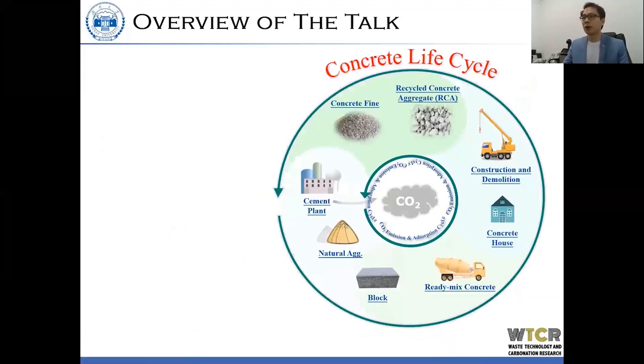Now a brief overview of what I'm going to look into today. The role of CO2, or how CO2 can make the concrete life cycle more sustainable. We know that CO2 is emitted from the cement plant and the amount is huge. So we can utilize the CO2 for curing cement blocks or ready-mix concrete. During the service life, depending on the type of application, CO2 can be reabsorbed back into the concrete, around 5 to 20%. And at the end of the service life, depending on how we recycle and handle the material, CO2 can take out another 5 to 10% of CO2 from the atmosphere into this material.